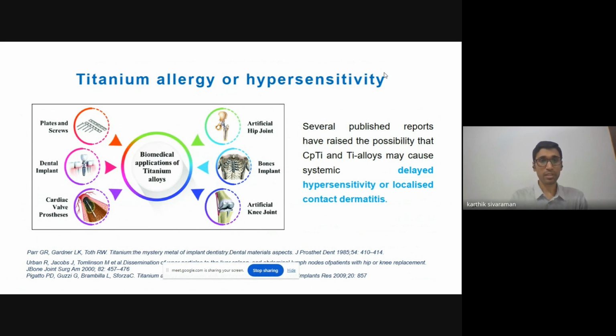So when we look at the titanium levels in our body, you approximately have 50 ppm exposure already, because titanium is routinely used in fashion products or even in sports wear, especially since it tends to impart a white color. When you place a titanium implant in a patient, that 50 ppm might rise to 100 to 300 ppm. And apart from dental implants, titanium has a various range of applications which are shown in the figure here.